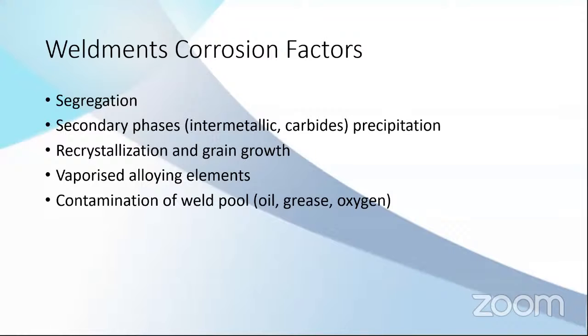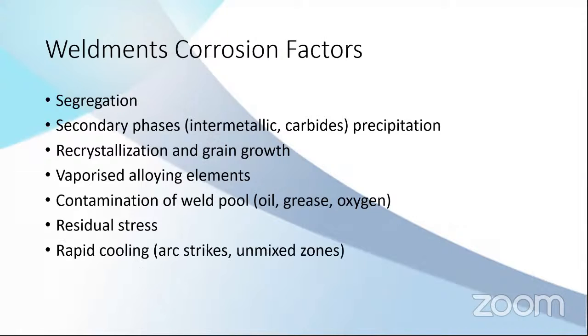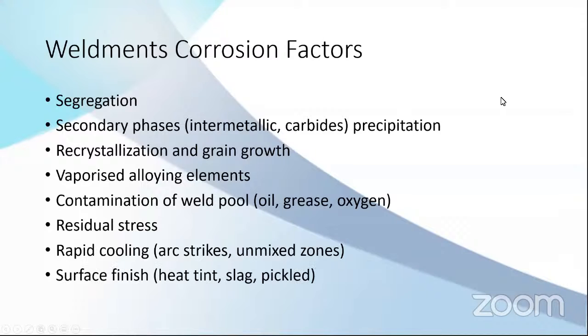Possible contamination of the weld pool from oil, grease, and oxygen. And when you weld, you apply a very high temperature, and it can give you residual stress after the weld is cool. Also, rapid cooling may happen during welding, especially in arc strikes or the area of unmixed zones. And surface finish. After the weld, you need to clean the surface again to avoid reduction of corrosion resistance. So you can find heat tint after the weld. You can have slag, and you can pickle the surface to get better corrosion resistance.